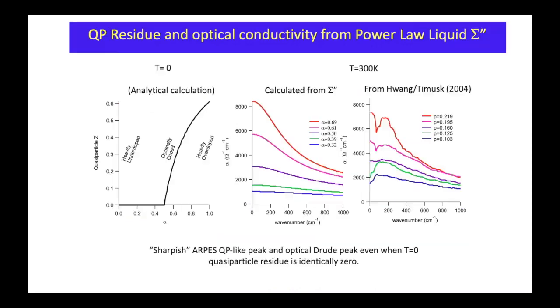Okay, so with this, we can also calculate optical conductivity. This is done at 300 Kelvin. So this is sigma 1 versus wave number, at 300 Kelvin for different dopings. Here, it looks like there's some Drude-like peaks, but they're not real quasiparticle, it's not Fermi liquid, and we can compare it to experimental measurements of the same, again, with the same scale, 2000 and 8000, et cetera, at similar doping levels.